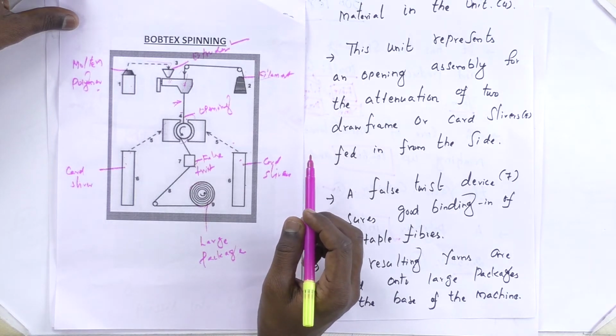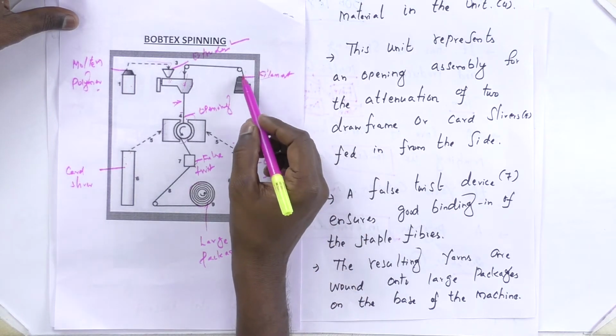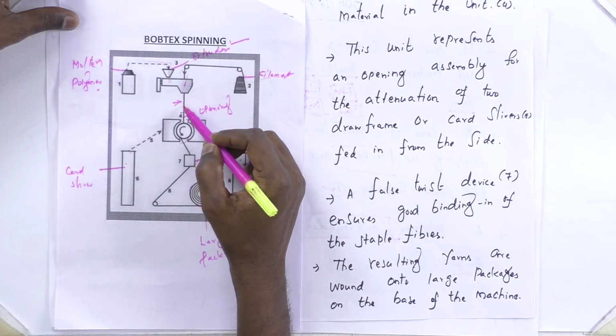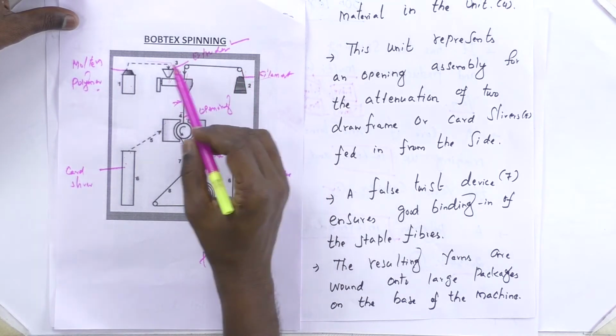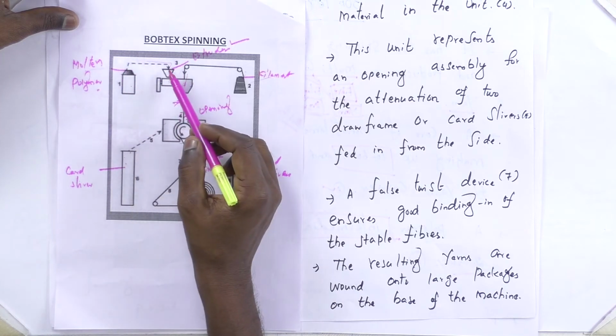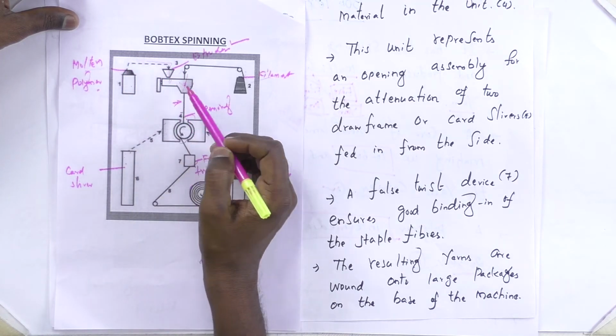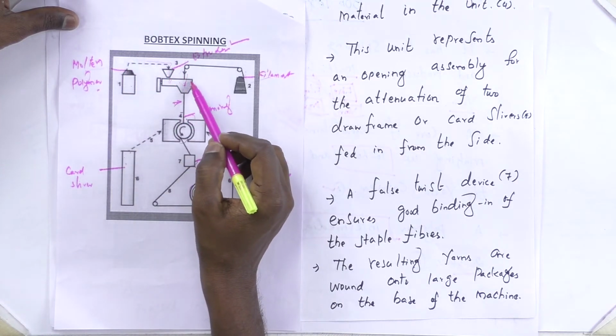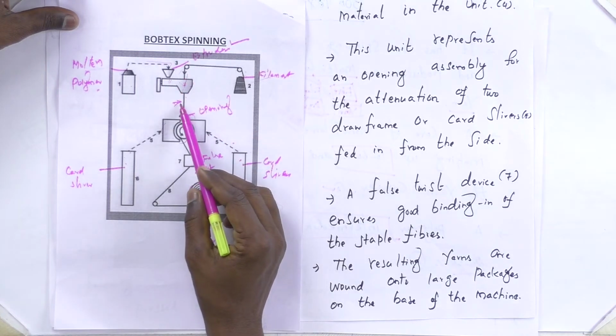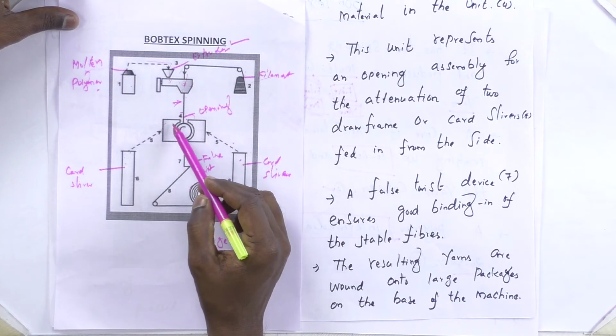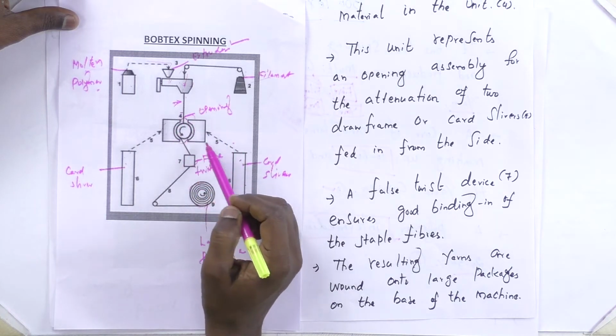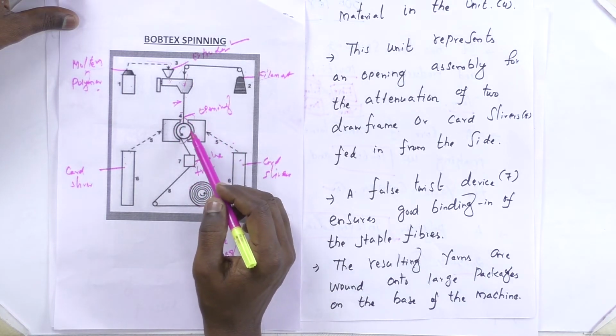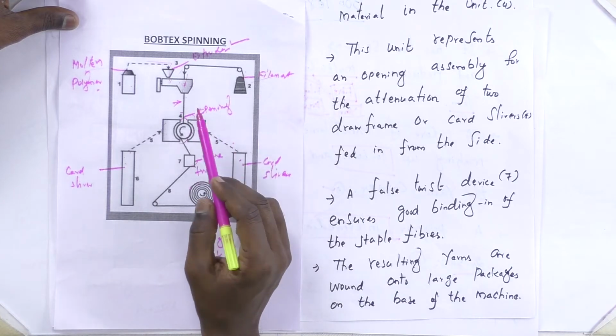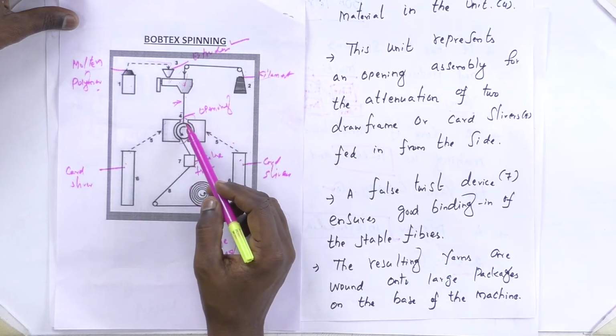So the first step of Bobtex spinning is the filament yarn is passed through the extruder. At the same time we flow the molten polymer inside the extruder. The polymer solution makes an outer layer of the filament. Before it gets solidified, the filament yarn is attached with the loose fiber which is coming from the slivers, which is opened thoroughly, and the loose fibers are attached with the surface of the filament yarn.